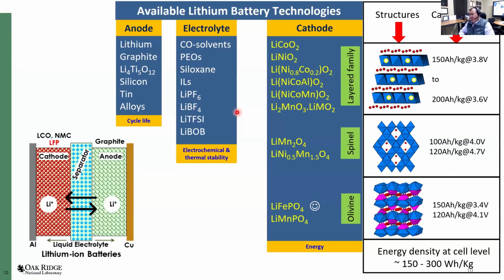and that's a phosphate. And in relevance to Morocco, we all understand that we are the major producer of the material in the world, and those opportunities can be linked to that, in fact. So what matters really is the capacity and voltage of these different structures. On the top, those structures are defined by how the lithium ion is really organized into this structure. So layer structure, you have lithium ions in between transition metal slabs, in the middle structure spinel, you have lithium ion moving through 1D tunnel, and more or less the olivines, you have 3D pathways for lithium ion moving into that structure.